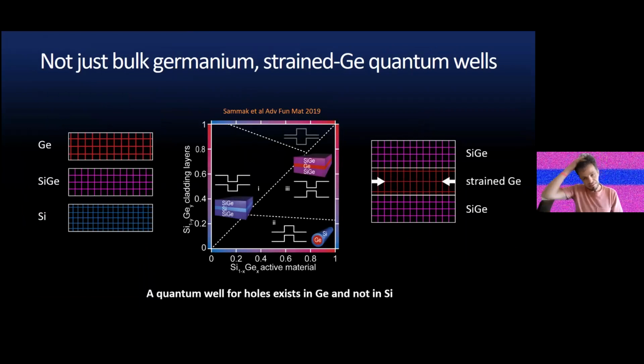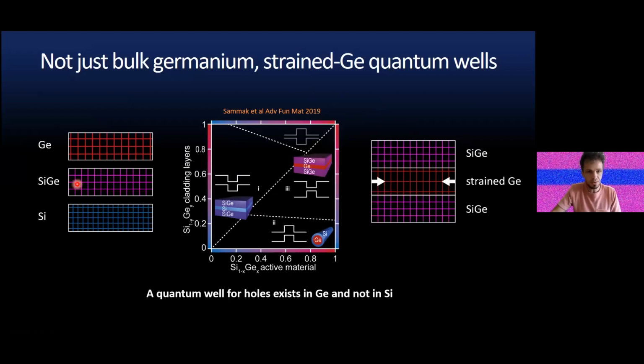So now let's dive a bit deeper into the platform. The key point to understand is that we are not really interested in bulk germanium, but germanium under particular conditions, which is strained germanium quantum wells. So let me show my pointer here. As you know, silicon and germanium have different lattice parameters. Germanium has a slightly larger lattice parameter, 4%, and silicon germanium is just a linear relationship in between.